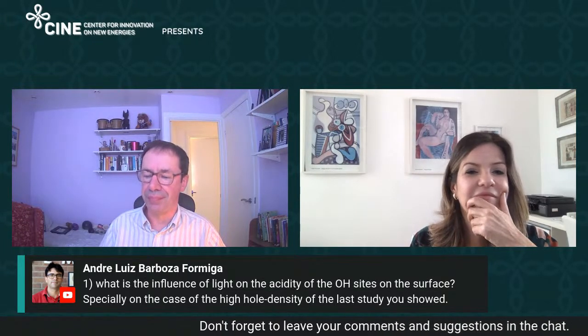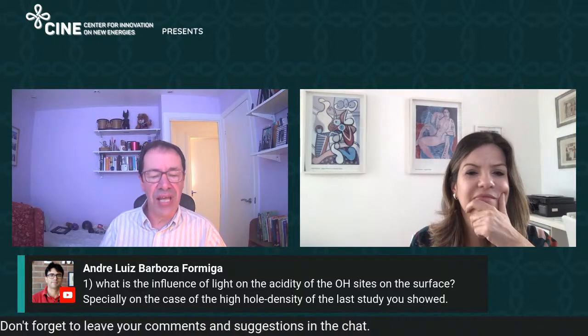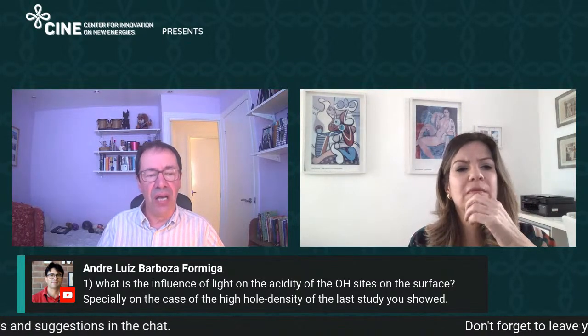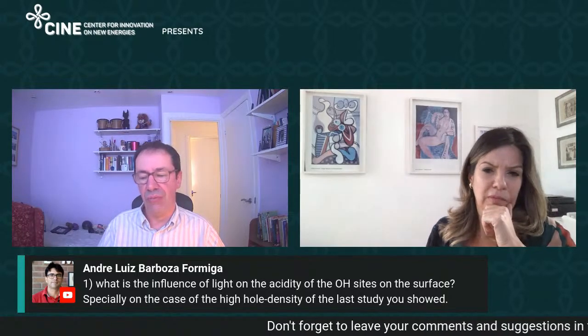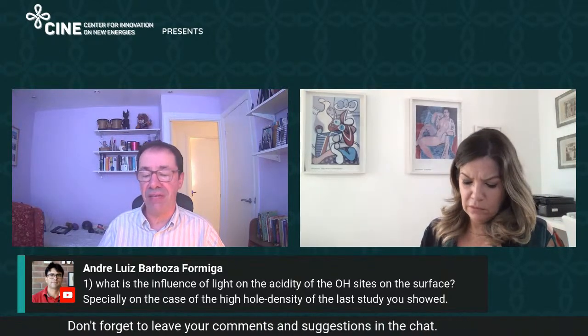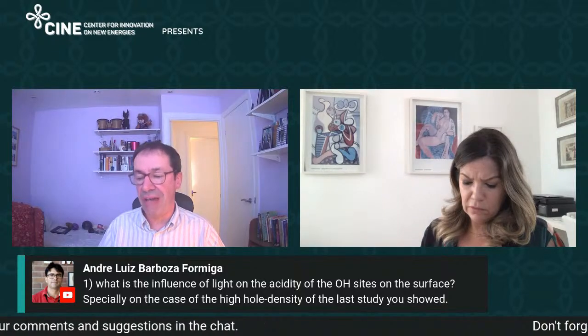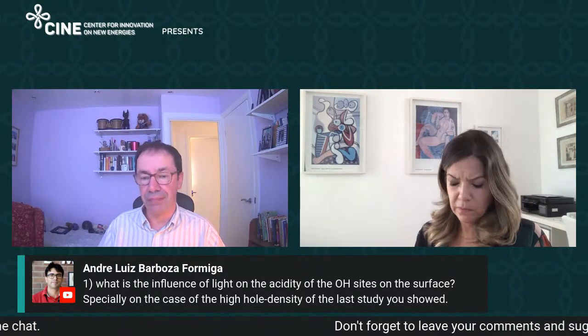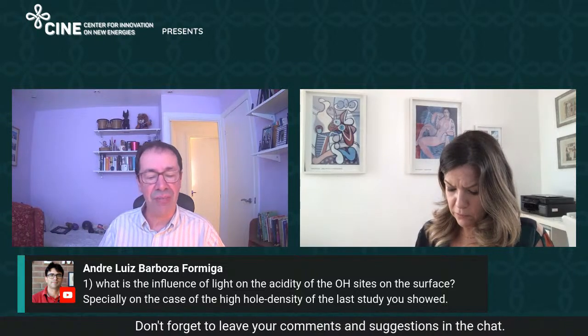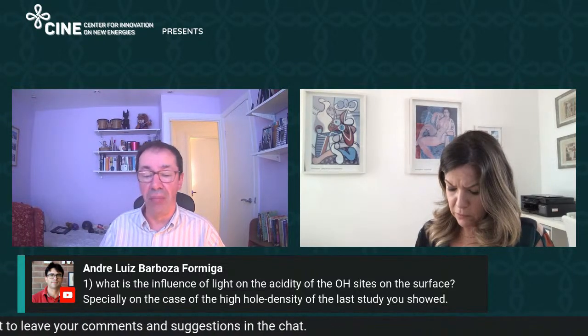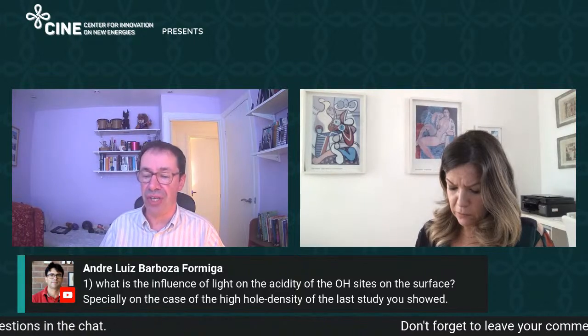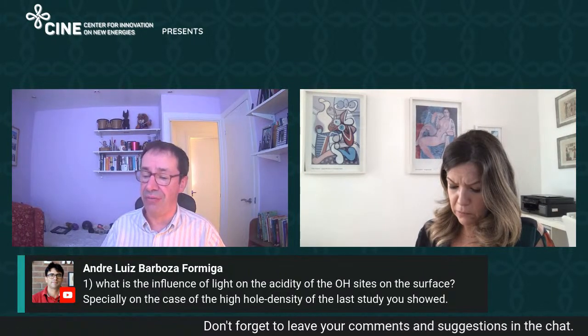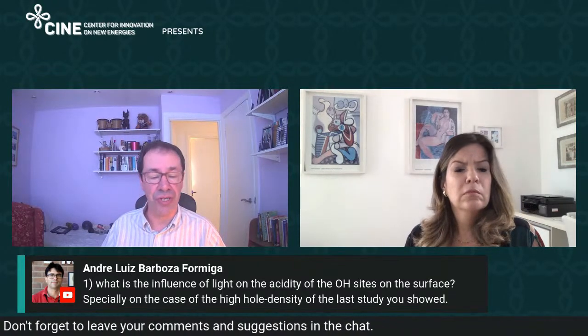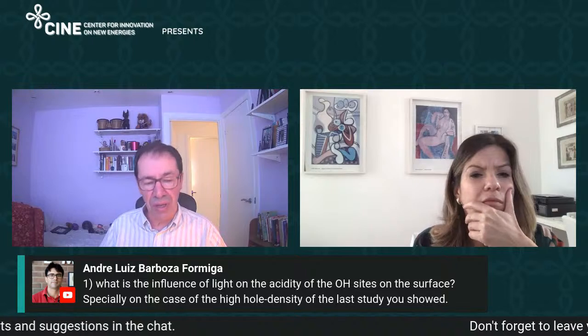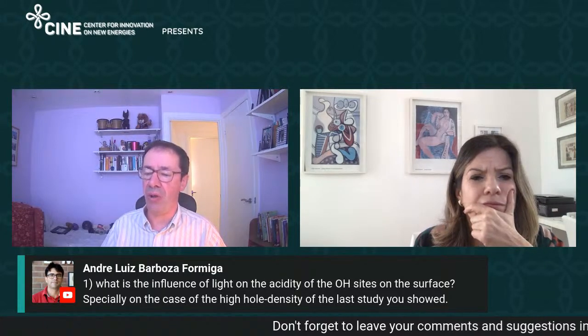So this is about the acidity of OH sites on the surface, and that's quite hard to understand. So as I mentioned, as you oxidize the surface, then you accumulate a large amount of charged carriers, and these charged carriers themselves will tend to change the band bending. And so as you accumulate more charge on the surface, the space charge layer becomes less effective at keeping those holes safe from electrons in the bulk.